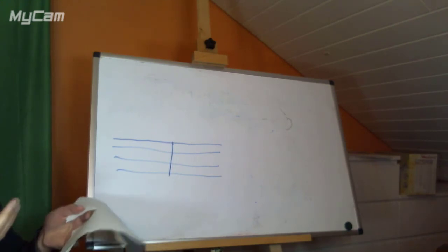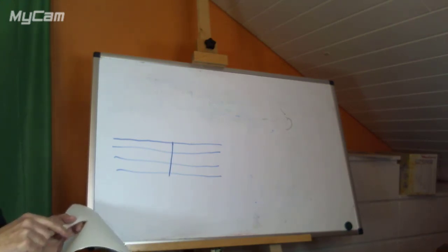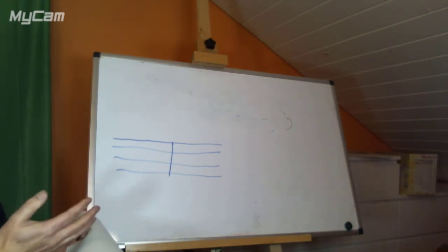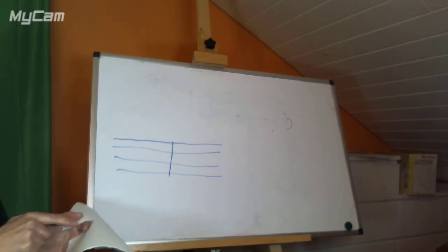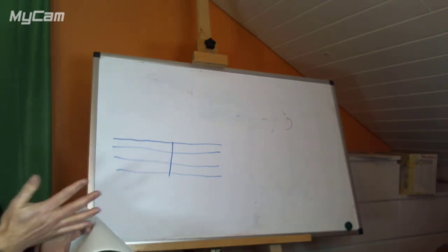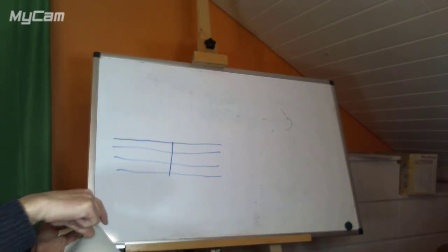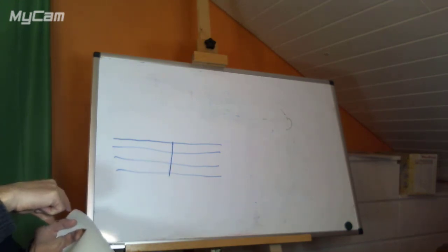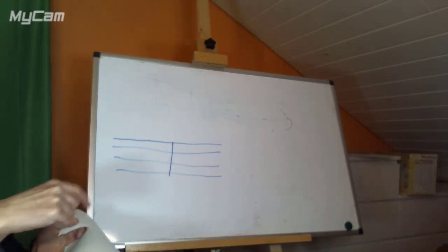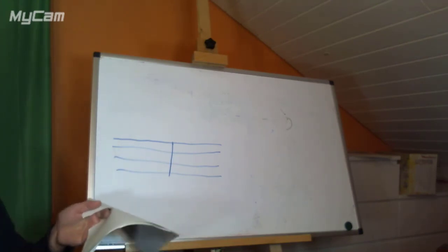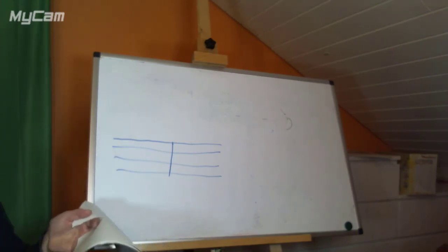This is good for growing things because we have a continuous growth on the edge of this growing edge. It's a continuous line edge, and our new atoms, or molecules, whatever they are, can stick here and go round and round and round and grow another layer, and then they can continue, and it never fills up, and so it never blocks. We don't get this steppy energy process.